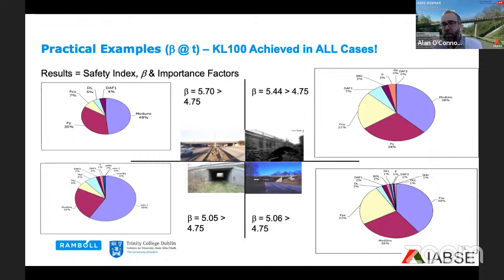In all cases, as Dimitris indicated in his presentation, we looked at the importance factors for the modeled variables and the distribution of the importance factors. We also looked at sensitivity analysis in all cases to ascertain the sensitivity of the computed beta value to the modeling of the variables, and to satisfy that we had adequate capacity. So again, through making operable the kinds of techniques which the other speakers have spoken about, through the guideline, which is consistent with the Eurocode formats, we were able to document adequate capacity of these structures and avoid costly replacement. That could be in terms of direct costs or indirect costs, and also enhance the sustainability of the solutions by avoiding unnecessary CO2 generation through documentation of adequate capacity of serviceable structures.